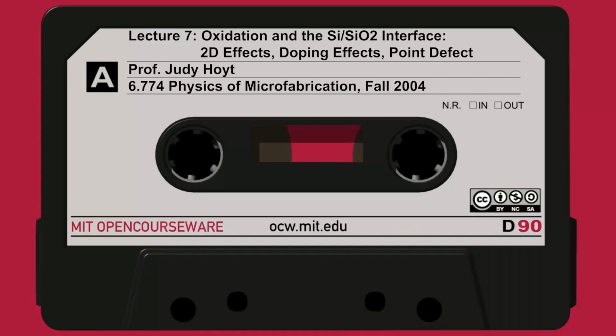It's going to be equal to EA on a flat surface, whatever that might be, say 2 electron volts, plus some extra terms. And there's a term that depends on the normal stress. Sigma n is the normal stress, so it's in the radial direction, sigma n, times some fitting parameter, VR, plus sigma t, the stress tangential to the growing surface, so along the circumference, times some other fitting parameter, volume Vt.